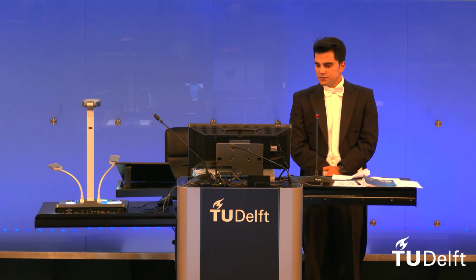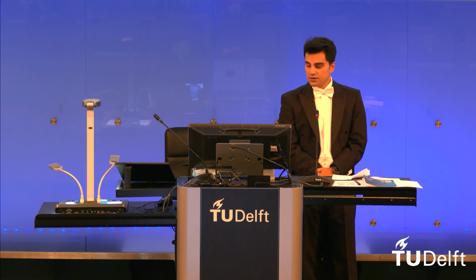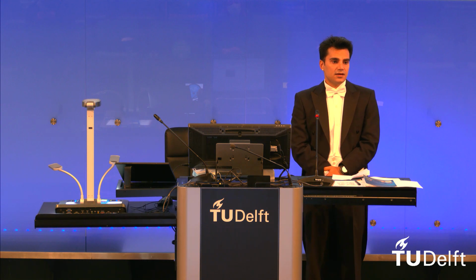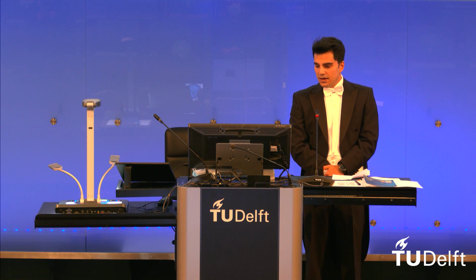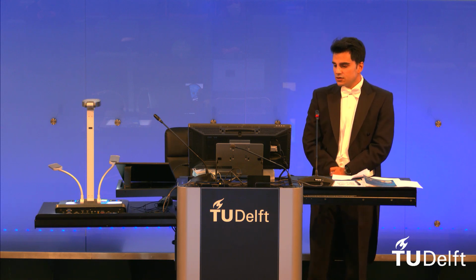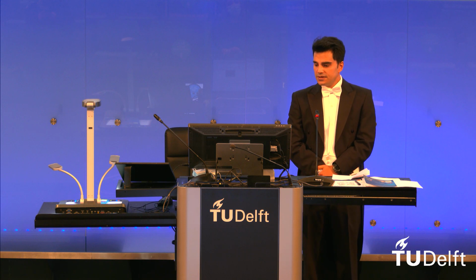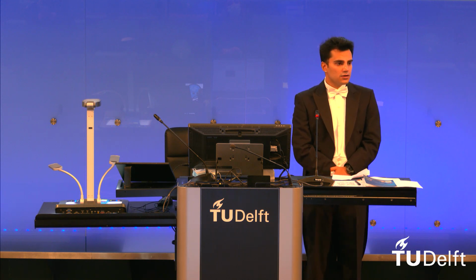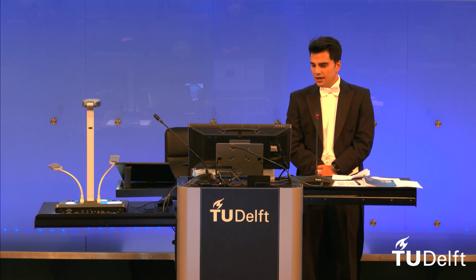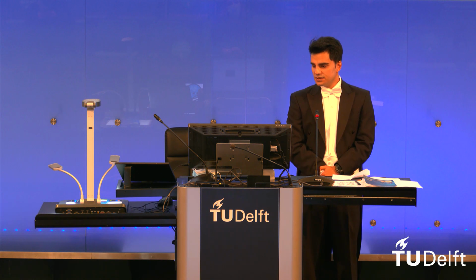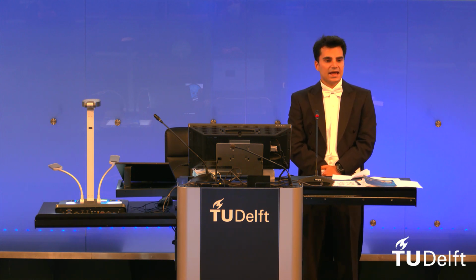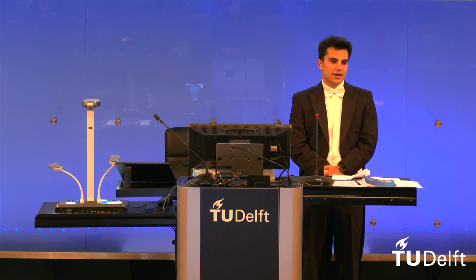We have some advantages for CT scan. We compared them with serial cutting, which is quite tedious and destructive, and we also have the idea of randomness when we do serial cutting. CT also has advantages compared to eddy current and ultrasonic technologies, which are proven technologies in the railway engineering field. And we concluded that CT could bridge the gap between the methods which can be used for macro crack analysis and the methods which can analyze the micro or nano cracks.